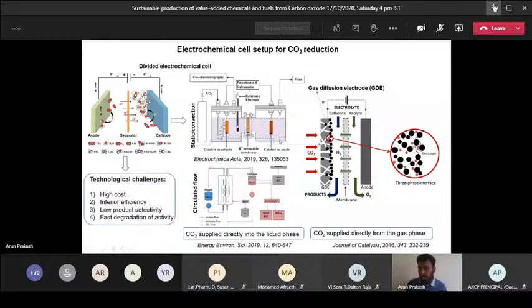The gas can easily pass through the pore and deliver to your catalyst surface without the need of dissolving in the electrolyte. This is the purpose of using a gas diffusion electrode. You can use a single compartment cell or a divided compartment cell. A single compartment cell has the issue of hydrogen evolution dominating CO2 reduction. But if you have a divided cell, you can use a proton exchange membrane, and the proton can move from one compartment to the other, avoiding hydrogen evolution dominating the CO2 reduction, and the product can also move sometimes.